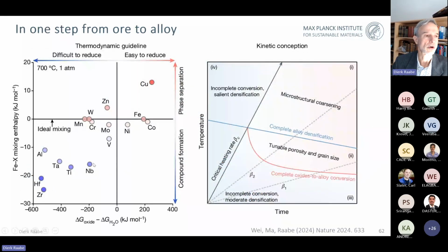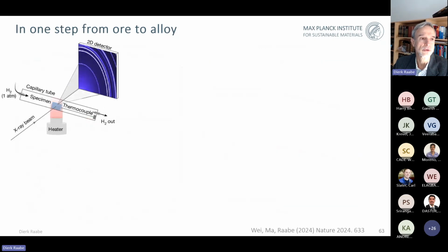You can put this a little bit on a thermodynamic map where you show here one axis, which is the iron plus the other element mixing enthalpy that tells you whether we talk more about compound formation or phase separation, which are both adequate targets. It just shows you where you should end up thermodynamically. And it shows, of course, the delta G of the oxide minus that for the water to show you whether it can be reduced under these hydrogen-based driving forces. You can equip that further with certain kinetic laws to say what I can do in terms of temperature and time to arrive at the desired microstructures also.